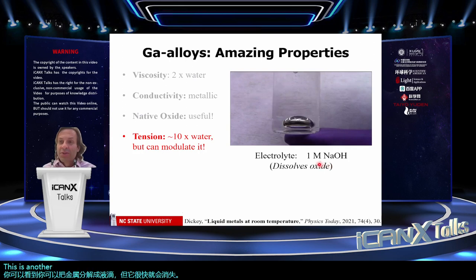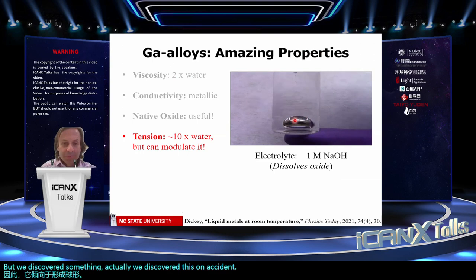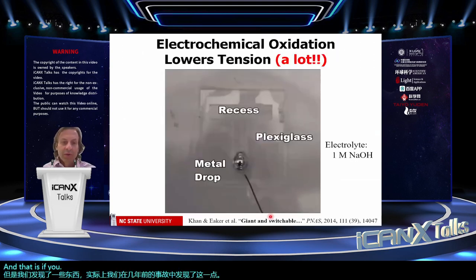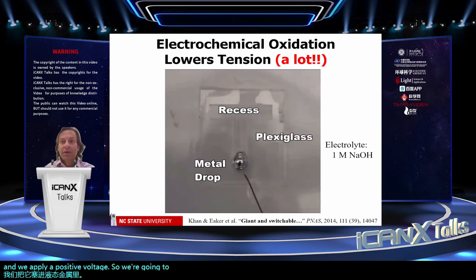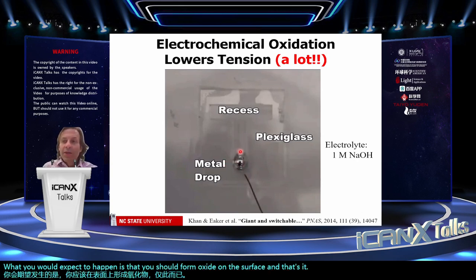This is another interesting thing about gallium. It has the largest surface tension of any liquid at room temperature. It's about 10 times that of water, so it's really large. And as a consequence, it tends to want to form spherical shapes. But we discovered something, actually we discovered this by accident a few years ago. And that is, if you apply a voltage to the metal, so you can see here's a wire, and we stick it into the liquid metal, and we apply a positive voltage. So we're going to try to cause oxidation on the surface of the metal. What you would expect to happen is that you should form oxide on the surface, and that's it. But in these particular conditions, we actually find that the surface tension gets lowered a lot.